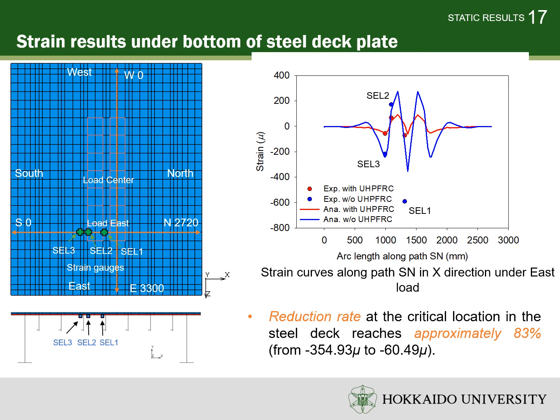Following the deflection results, the strain data on the bottom of steel deck plates are also investigated. The right figure shows the transverse strain distribution under load east along path SN where the strain gauges are located. It can be observed that the analytical curves show an acceptable agreement with the experimental data, except for the strain results at SEL1 for the model without UHPFRC. This may be because the mesh at the local region above the middle stiffener is not fine enough to capture the strain behavior at SEL1.